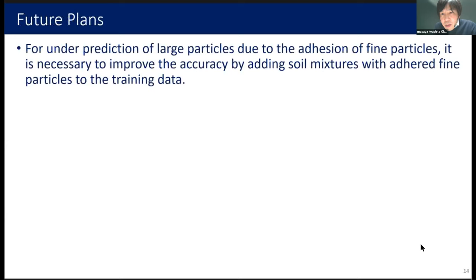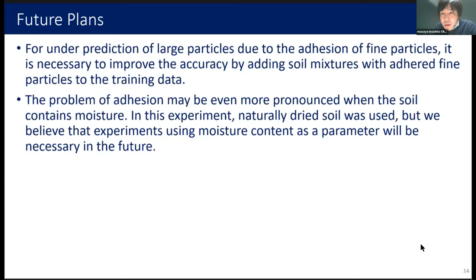The following are prospects of this research. For under-prediction of large particles due to attachment of fine particles, mixed soil with attached fine particles should be added to the training data to improve accuracy. The problem of adhesion may be even more pronounced when the soil contains moisture. In this experiment, we used naturally dried soil, but we believe that experiments using moisture content as a parameter will be necessary in the future.